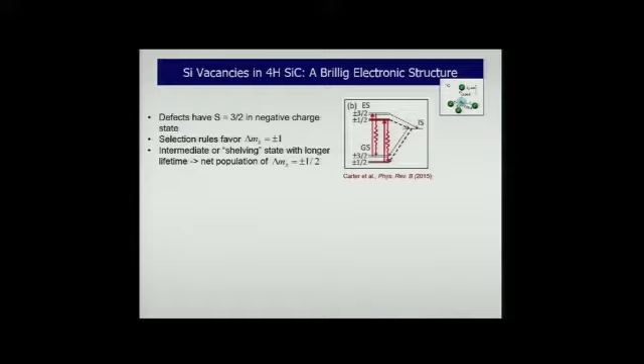What's interesting about this electronic structure is what is called the intermediate state, and is also called a shelving state. Shelving in the sense as you put it on the shelf. Shelving as you make a transition, and the strength of these dotted lines indicates the strength of the transition from the excited spin states to the shelving state. So if we excite from the ground state plus or minus 1/2 to the excited state, you see a very strong transition over to the shelving state. That shelving state then has a relatively strong transition over to the ground state plus or minus 1/2.